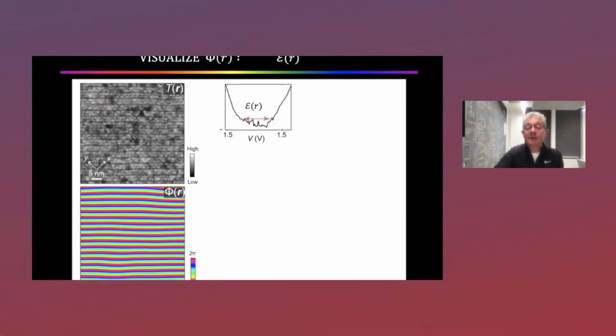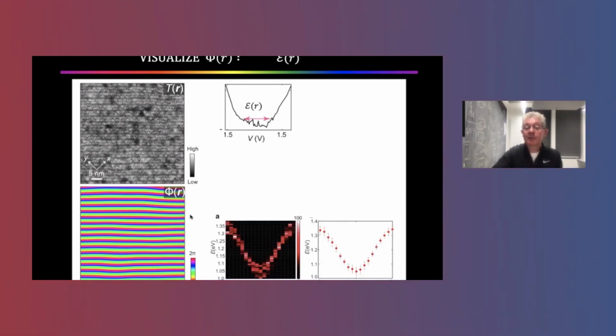All right. So let's take that at face value. We know the phase everywhere in this field of view. We know the charge transfer energy everywhere in that field of view. So we can plot a 2D histogram of charge transfer energy versus phase and reduce that to a curve. Charge transfer energy versus phase in 17% BISCO looks like the bottom right-hand curve there, measured. You can see the charge transfer energy is changing by more than 0.3 volts. It's amazing.